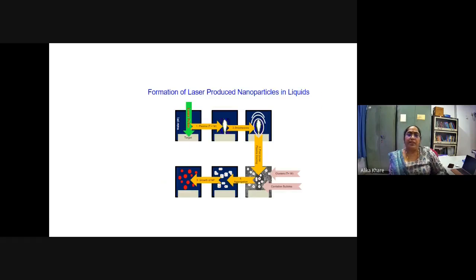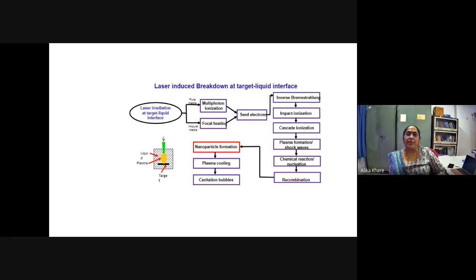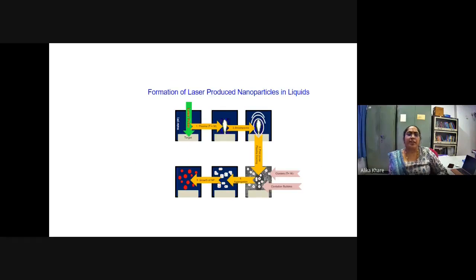So this is the scheme which we have applied to synthesize the nanoparticles. This is the pictorial demonstration of the same flow chart here: the laser is falling onto the target, plasma is being formed, followed by the formation of shock waves and the formation of nanoparticles, agglomeration of the nanoparticles, and finally we get the stabilized nanoparticles.